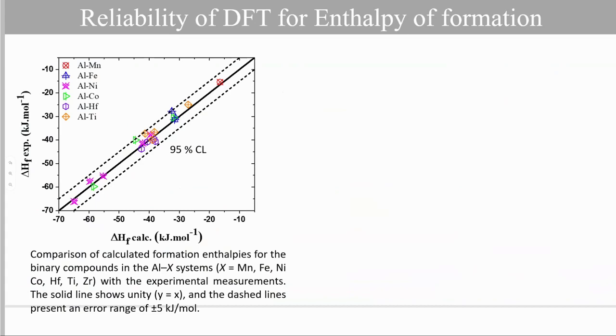So what is the reliability of the DFT simulation for the enthalpy of formation? This is illustrated in this figure. For aluminum transition metal compounds, we represent the predicted enthalpy of formation versus the experimental one. And we can see that for this family of compounds, we are within the so-called 95% confidence level, that is within the margin of experimental error. So for metals, DFT simulation is very accurate, at least in predicting the enthalpy of formation.